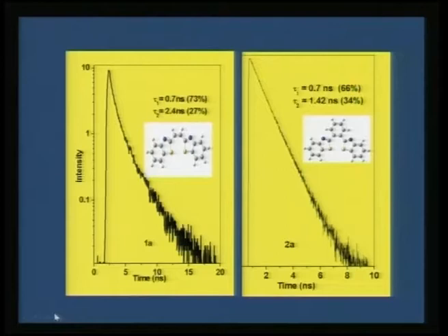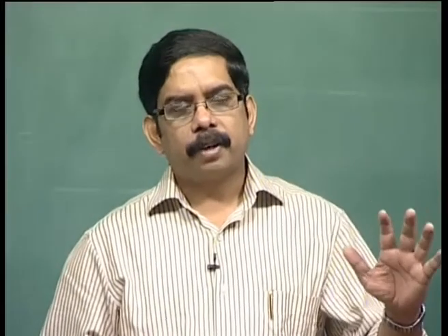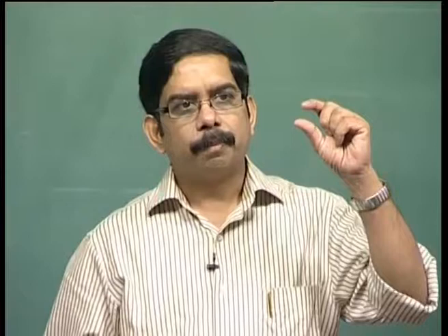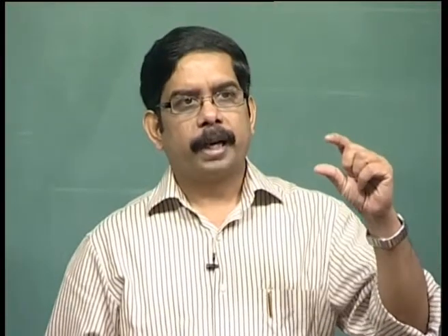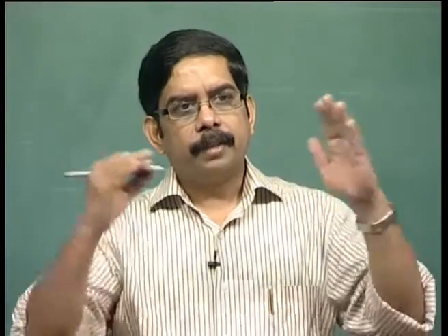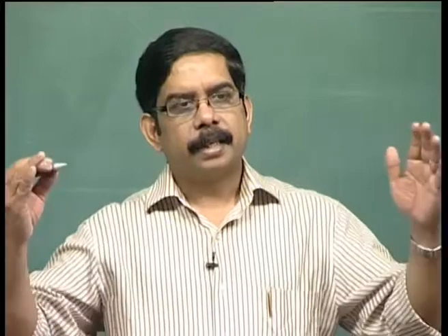As a result we can make a general conclusion that the featured emission for thiazoles is mainly because of an extended charge resonance which is spread throughout the ring, which brings down the HOMO-LUMO gap, and because the HOMO-LUMO gap is smaller, the emission is now involving the blue, green and red region. As a result, your full width at half maxima is always above 150 nanometer.